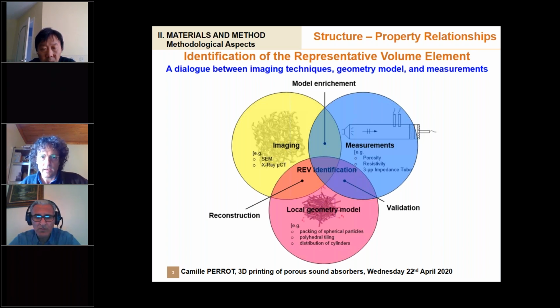So what are the imaging techniques? And then the model, the local geometry model, whether you are dealing with packing of spherical or aspherical particles, polyhedral tiling if you want to model foams, and distribution of cylinders if you are tackling the problem of fibrous media. And then once you have established a model, or a potential representative elementary volume, you solve numerically the equations governing the transport properties you want to derive from this geometry, and you need a validation.